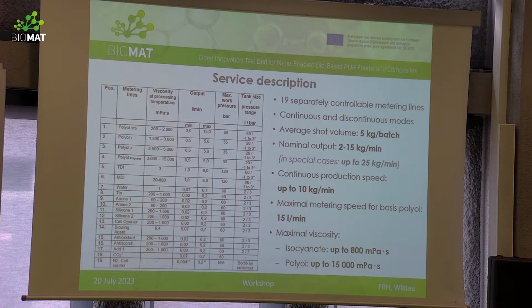Some additional information: we designed our line with a maximal metering speed of the basis polyol up to 15 liters per minute. And regarding the viscosity, for the isocyanate part up to 800 millipascal seconds, and for the polyol side up to 15,000.